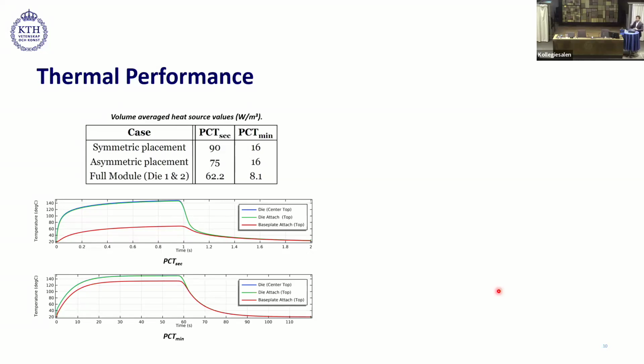We ensured that the temperature cycling, or the junction temperature, inside the module remains the same across all the cases. Therefore, we adjust the heat losses accordingly. Another thing to note here is that the base plate attached solder layer temperature cycling is different during PCT-sec and PCT-min. In PCT-min, the base plate attached solder layer exhibits higher temperature cycling.